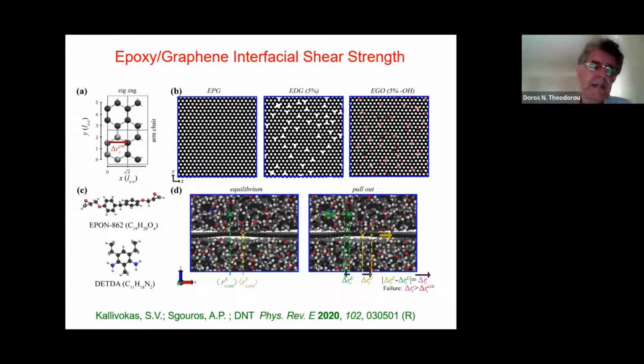And having equilibrated this interfacial system with 3-dimensional periodic boundary conditions, we essentially performed experiments. We performed experiments which imposed a force on the graphene towards the right, and an equivalent opposite force on the polymer towards the left, and observed how the system would respond to the imposition of this force that shears the interface. When the force is very low, nothing happens. Essentially, the system continues to fluctuate. But when the force is sufficiently high, then there is damage of the interface. You get essentially pull out of the graphene with respect to the polymer.